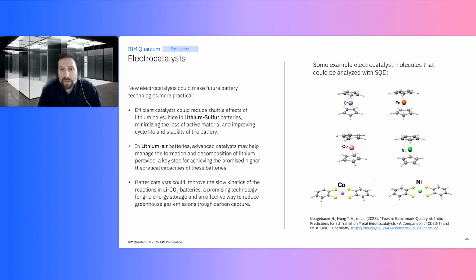So new electrocatalysts could make future battery technologies more practical. For example, they could reduce the shuttle effects of lithium polysulfide in lithium sulfur batteries. And so they would contribute to reducing the loss of active material and improve again cycle life and stability of this battery. In lithium air batteries, we could use advanced catalysts to manage the formation and decomposition of lithium peroxide, which would then represent a key enabler for achieving the higher theoretical capacities of these batteries.